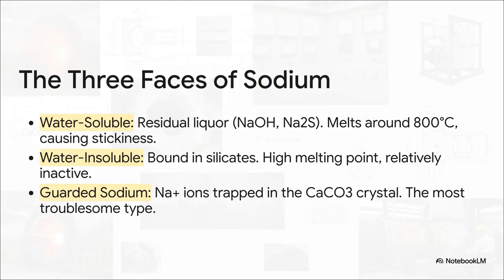And here's the thing. Not all sodium is created equal. You've got your water-soluble stuff from leftover liquor. That melts around 800 C and causes stickiness. Then there's the insoluble sodium, mostly locked up in silicates. It's relatively harmless. But the real villain here, the one that bites you in the field, is what's known as guarded sodium. These are sodium ions that literally get trapped inside the calcium carbonate crystal lattice itself. You can't wash it out, and it gets released at the worst possible time, right in the heart of the kiln where it can cause the most damage.